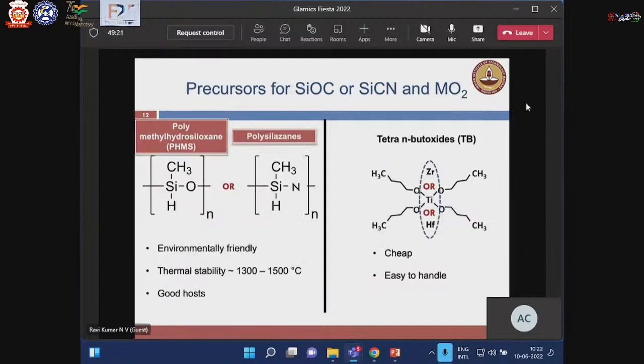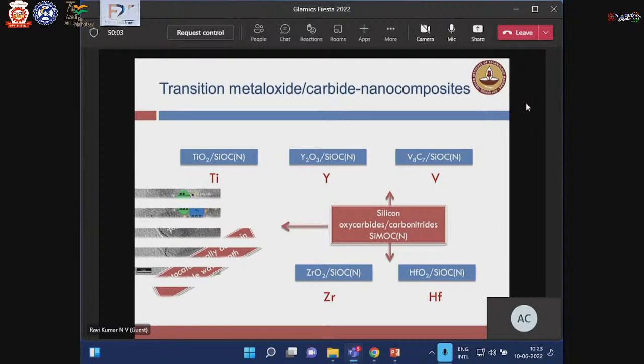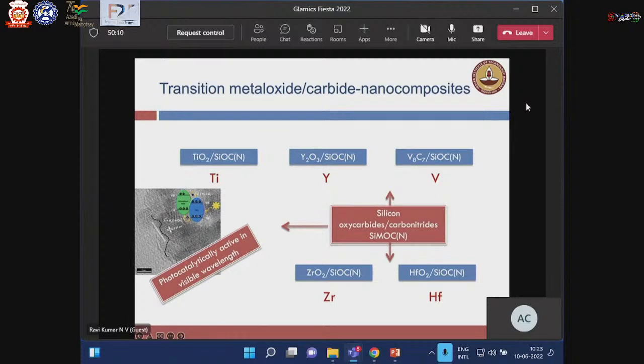What we have been doing is modifying these siloxanes with precursors of transition metals. We use tetra butoxide for transition metals so that we in situ crystallize transition metal oxides in them and make them thermally more stable, so that they can be stable till around 1800 or 1900 degrees Celsius, for functional applications as well. It is also important to note that the ceramic yield is quite high in these. We have incorporated zirconium, hafnium, vanadium, yttrium, titanium and so on.